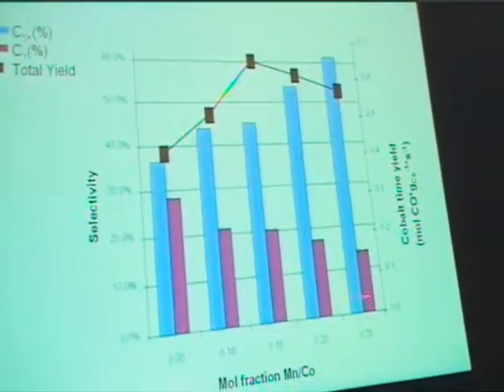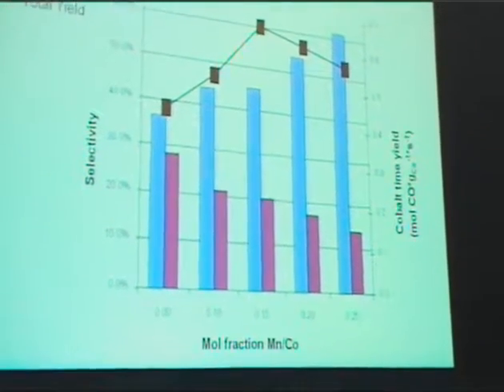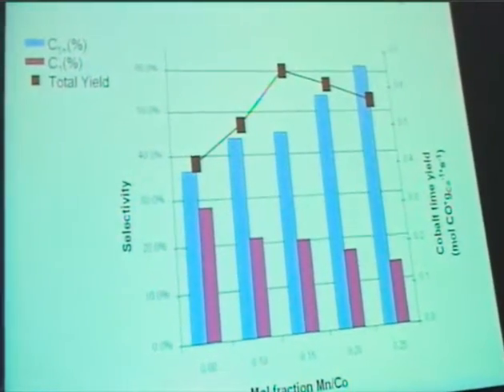We have also varied the amount of manganese. This plot summarizes the results: less methane and more C5+ when you add more manganese. There is an optimal yield at intermediate manganese-to-cobalt ratios. When you analyze these samples with hydrogen sorption, you find that the samples at intermediate loadings absorb the most hydrogen. After reduction, we have samples with about 6 to 8 nanometer cobalt particles.